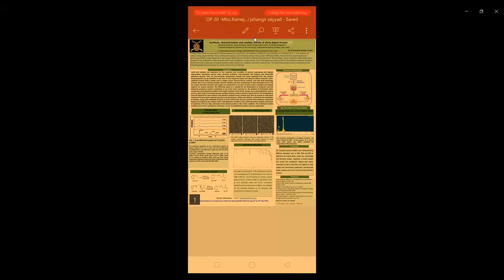The characterization using XRD, SEM, EDX and FTIR was done. The structural property was investigated by XRD over 2 theta values in the range of 10 to 80 degrees. The planes at 101, 110, 112 and 211 indicate the presence of the yttrium zirconium phase.